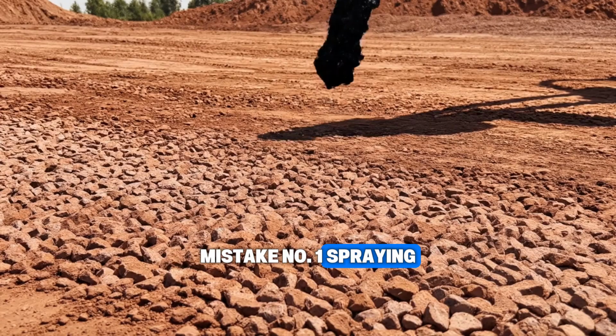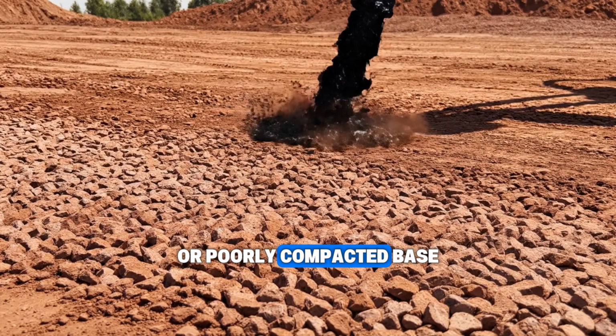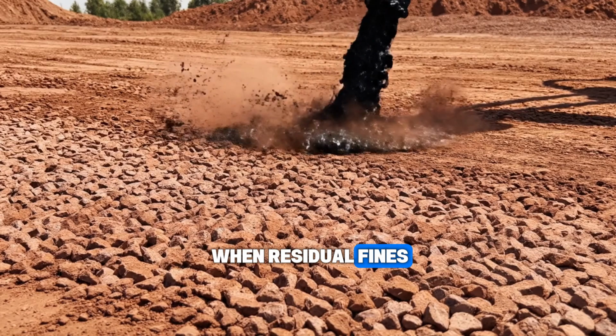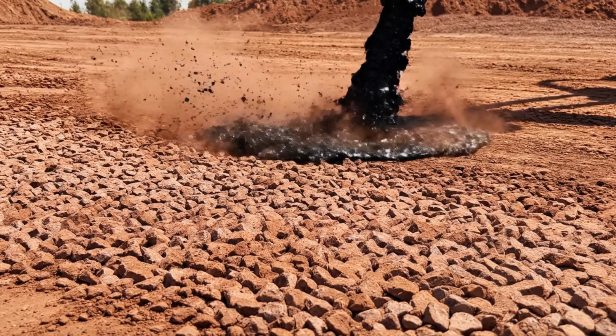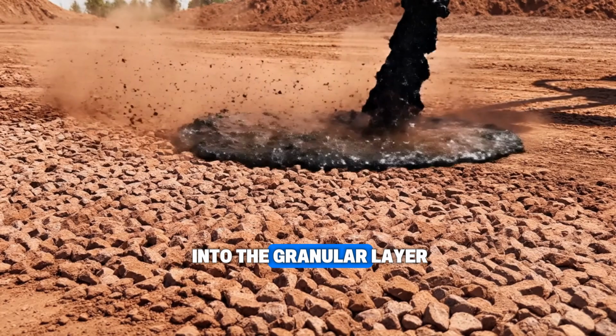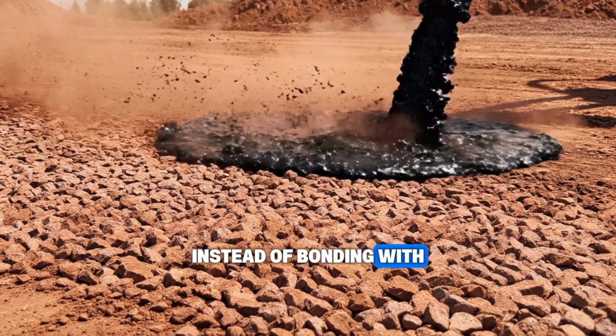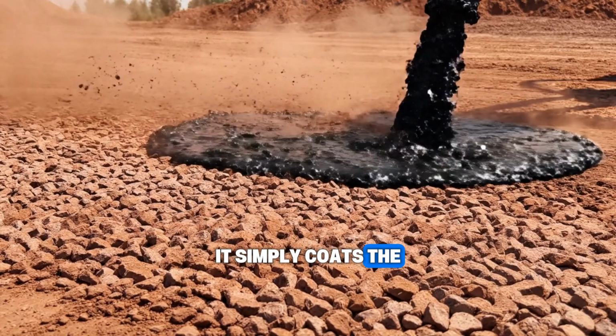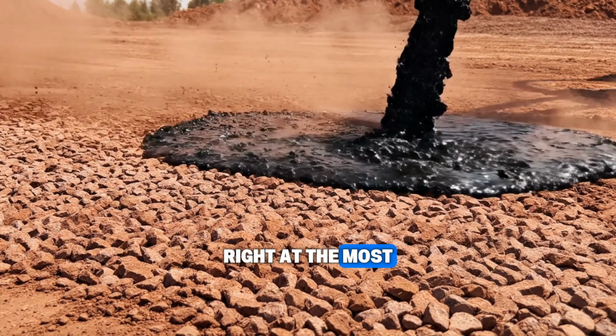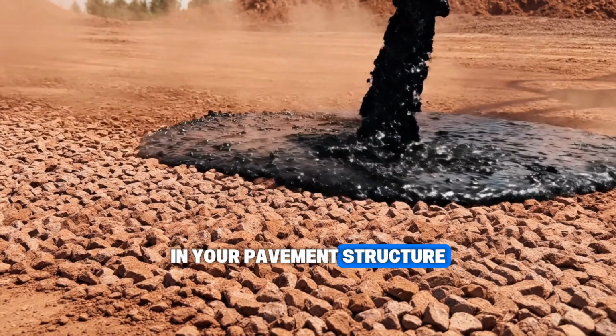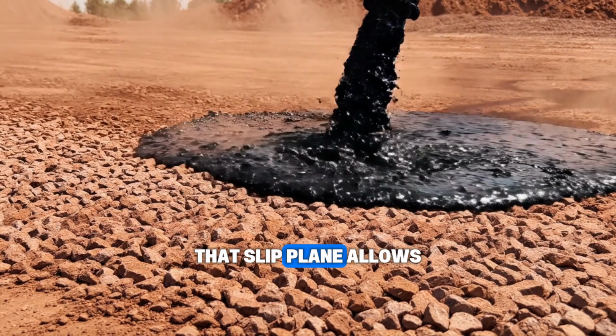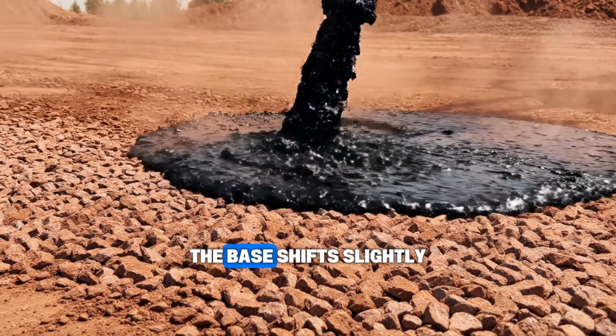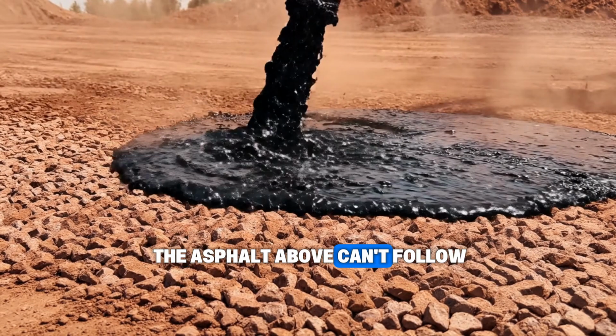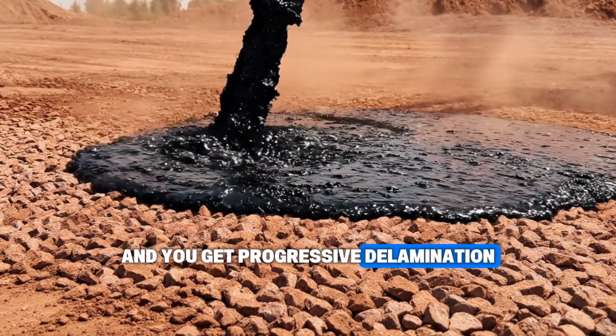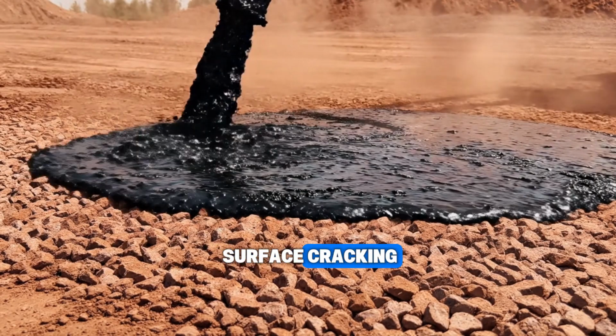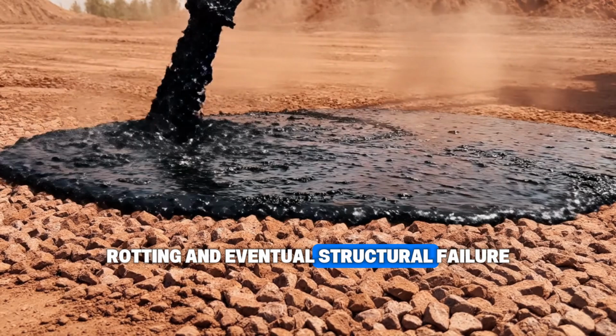Mistake number 1: spraying prime coat over a dusty or poorly compacted base. When residual fines and loose particles sit on the surface, the bitumen cannot penetrate into the granular layer. Instead of bonding with the base material, it simply coats the dust, creating a slip plane right at the most critical interface in your pavement structure. Under heavy wheel loads, that slip plane allows lateral movement. The base shifts slightly, the asphalt above can't follow, and you get progressive delamination, which shows up as surface cracking, rutting, and eventual structural failure.